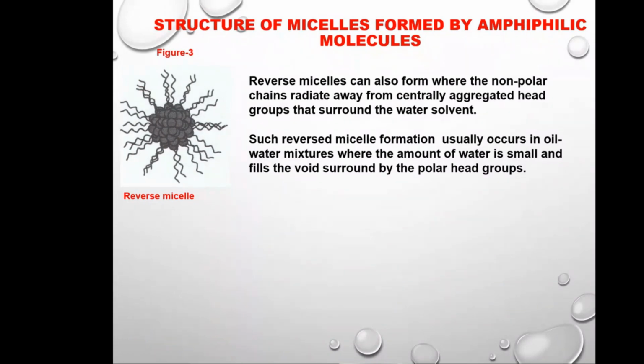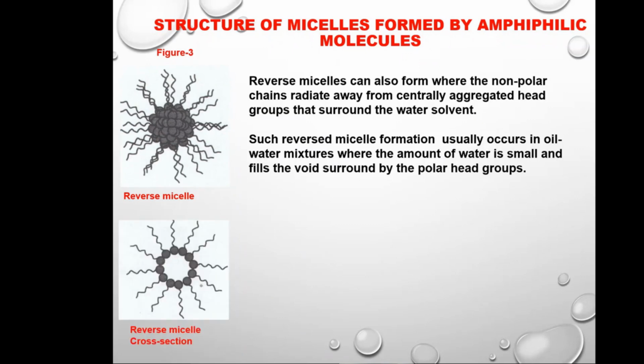Another possibility of arranging such molecules is the reverse micelles. We can have structures where the heads stick together and the chains are outside of this composition. Usually such structures can be seen in oil-water mixtures where the amount of water is small and it fills only the void surrounded by the polar head groups.